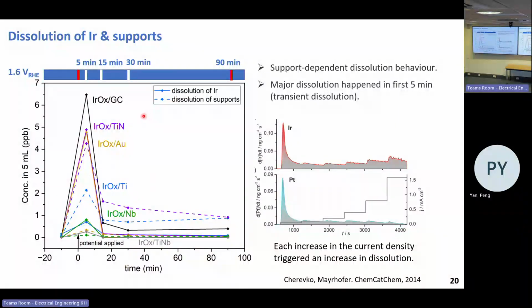The electrolyte has been taken out at 5 minutes, 15 minutes, 30 minutes, and 90 minute intervals during the reaction to look at the metal dissolution from both iridium and the supports. Major dissolution happened in the first 5 minutes, which is in line with the literature, and it's called transient dissolution. It's because of the potential jump at the beginning of the experiment.